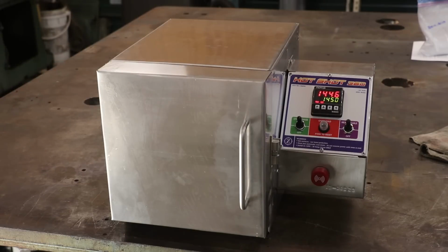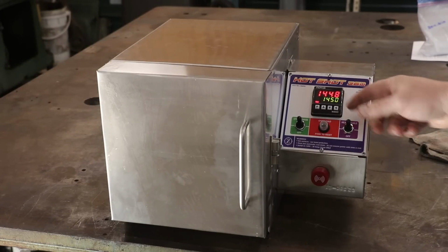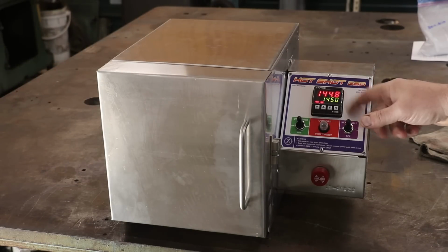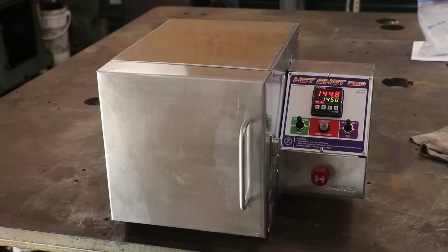Well, the oven's been running now for probably about 20 minutes, and we're getting right up on that 1450 degrees, 1448 here. I noticed it was climbing real fast until it got to about 1430, and then it started cycling the heat elements in there so that it's not just going to blow past this number. So it should keep that temperature right there around 1450. But as soon as we get there, all right, 1450, I'm going to start a timer on my phone here for about 30 minutes, and then we'll come back and we'll do the quench. So anyway, we're hovering right there around 1450 right now.